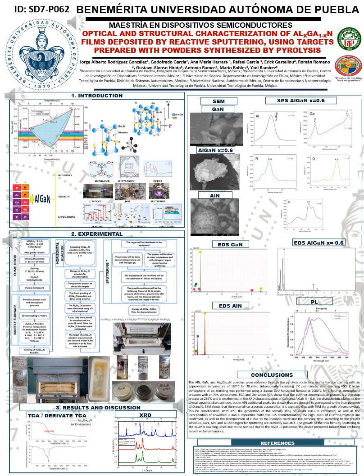Once the thin films have been obtained by sputtering and reactive sputtering on the substrates, the morphological, structural, and optical characterization will be carried out. Conclusions. The GaN and AlGaN powders were obtained through the pyrolysis route in a muffle furnace starting with an approximate temperature of 180 degrees Celsius for 20 minutes. Subsequently increasing 1 degree Celsius per minute, until reaching 400 degrees Celsius in an atmosphere of air. Nitriding was performed using a 3-zone CVD horizontal furnace at 1000 degrees Celsius for 1 hour at atmospheric pressure with an ammonia atmosphere.